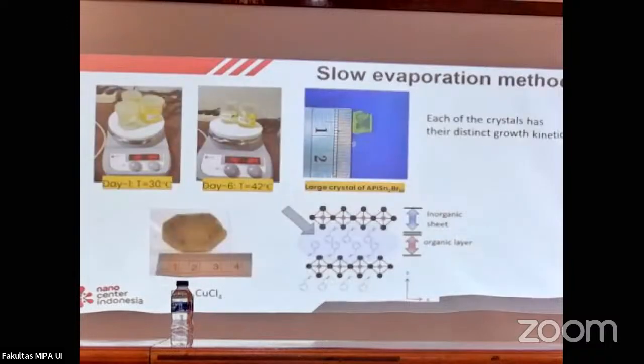Okay. So to give you an idea of how we grow the perovskite, the whole thing is basically simple wet chemical synthesis. We pour in several of our precursors, and then, depending on the structure, some cases can be grown in only about 6 days, and then to get such a nice large crystal, there is some post-production to get a good transparent crystal.